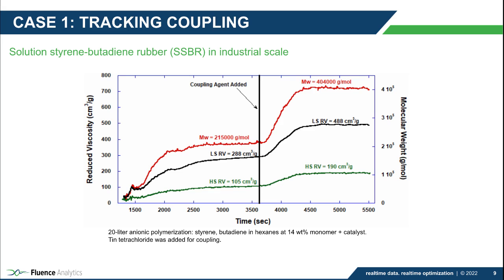Continuous monitoring allows establishing the optimal point for addition of the coupling agent, for example, earlier, after observation that the first plateau has been reached, based on the desired final molecular weight, and detecting shear thinning or thickening behavior, as they are directly related to processing and rheological properties.